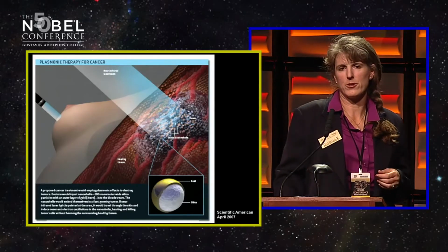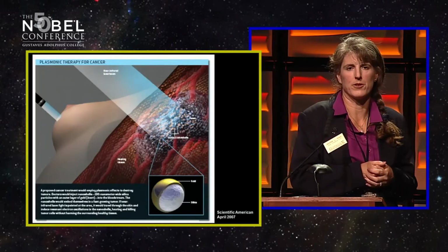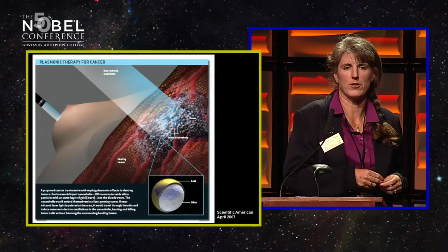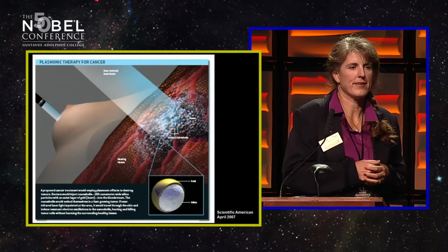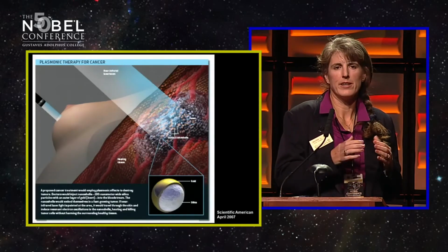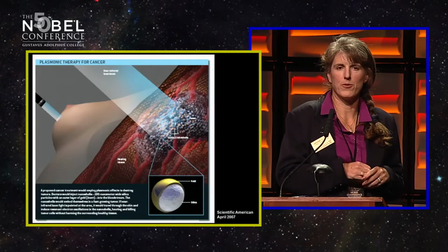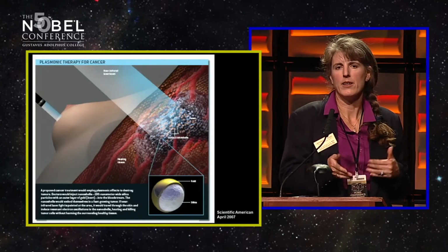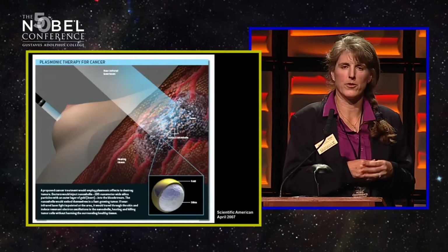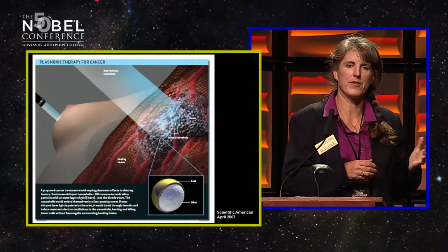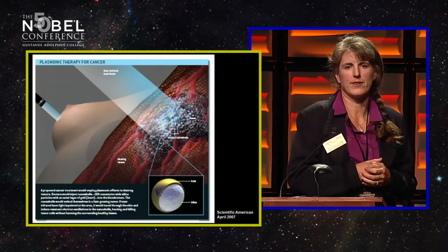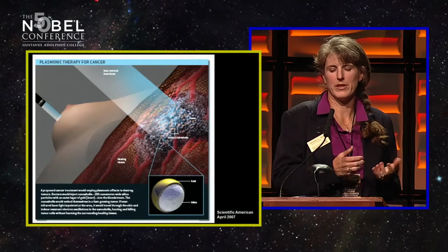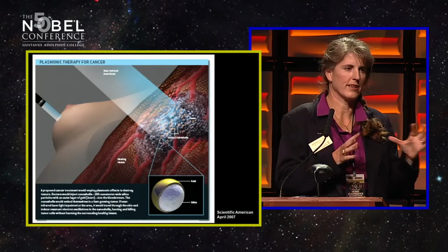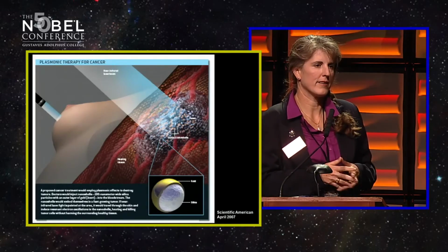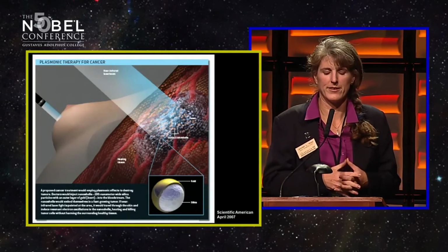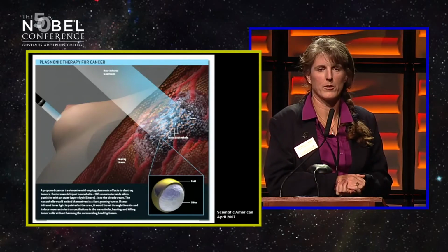In areas where you have tumor growth, you have very rapid growth of new blood vessels to keep up with the growth of the tumor. These new blood vessels tend to be very poorly formed and will have gaps between the cells on the order of 400 to 800 nanometers in size. So if you can make nanoparticles, you can start to escape through these gaps. You want to make them big enough, though, so that they're not escaping into normal tissues or being filtered through the kidney. So you need to understand the different biological access points and design your particles to fit into a sweet spot where they'll accumulate in the tumors.